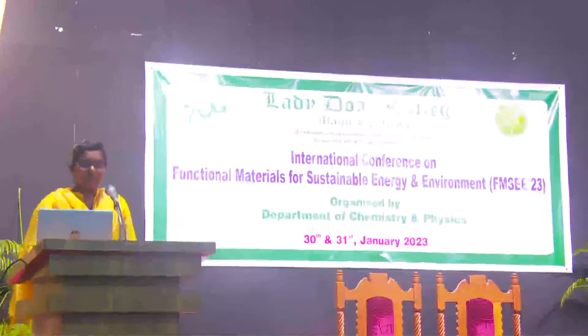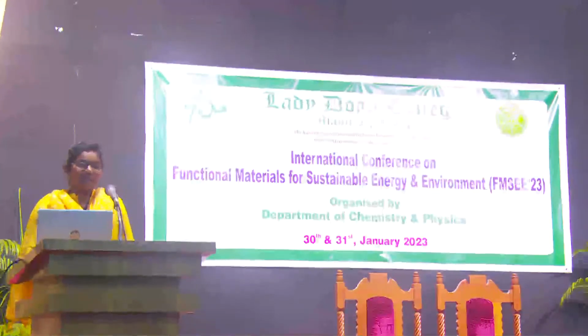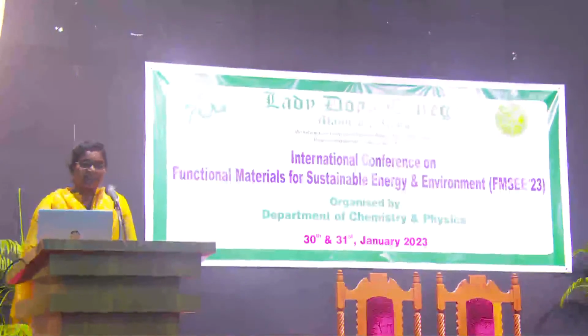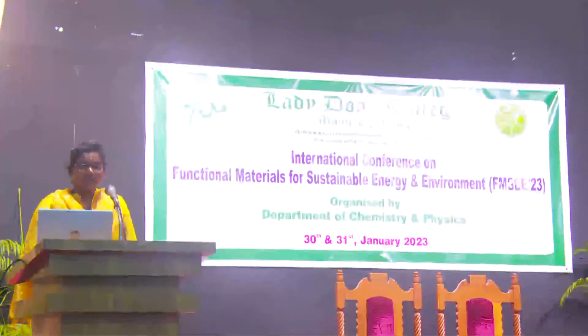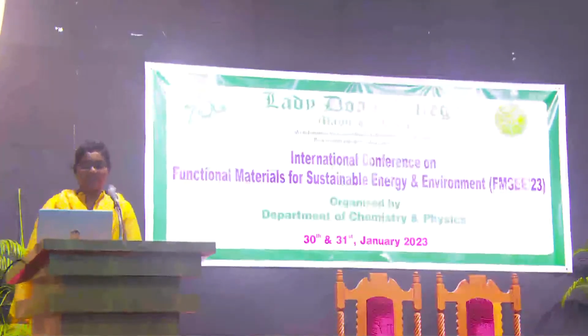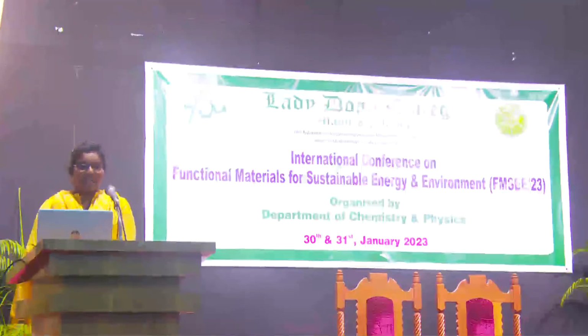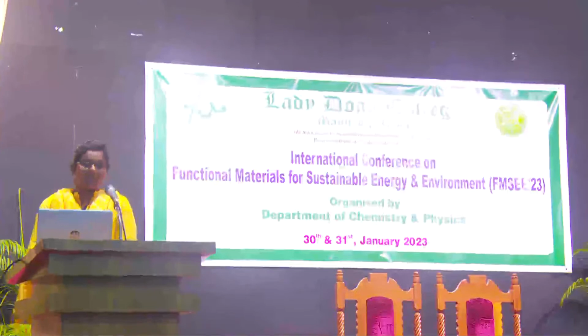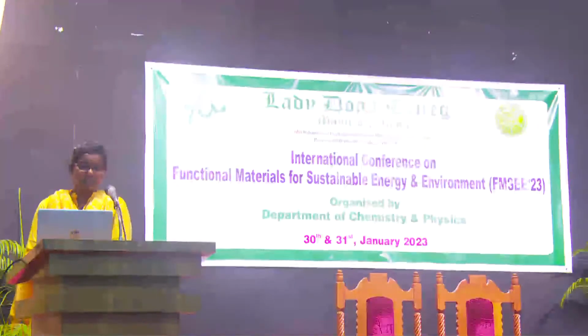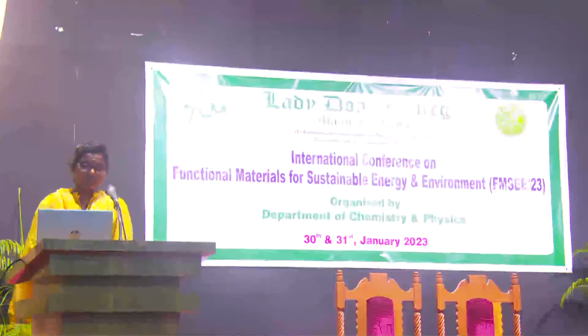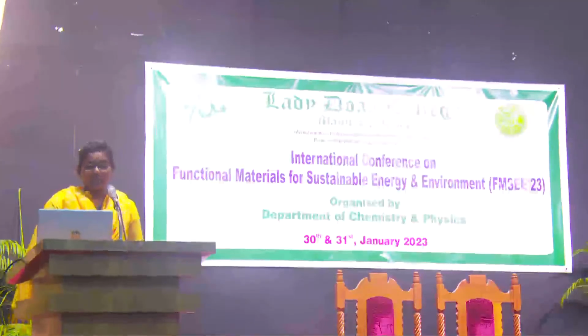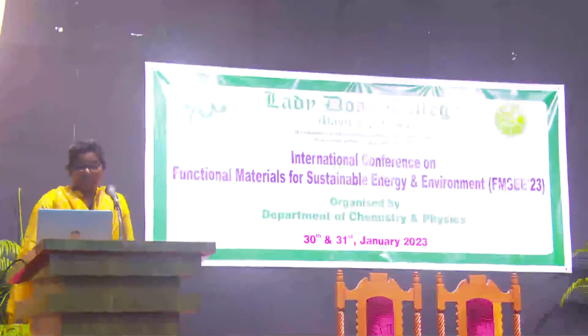Dip coating process of mine. The glass plate is taken and one side is taped completely and the other side is fully cleaned with acetone. 30 ml of PVA gel is taken and the non-taped side of the glass is dipped in 3 continuous steps, and after 15 minutes the second layer of organic dye. Finally these 2 layers of polymer and organic dye were dried, and then the tape was removed from the second side.